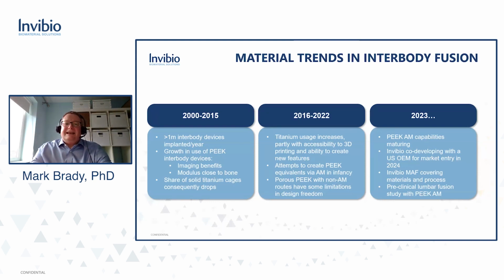By the middle of the 2010s, however, we saw titanium use increase. And that was partly due to a trend towards expandable devices, but also accessibility of titanium 3D printing that enabled the ability to create new features, porous structures, and the ability to modulate some of the device stiffness. We saw the first attempts to create PEEK-based devices, but they were very much still in their infancy, and the non-additive manufacturing approaches to porous PEEK still had some design limitations to them.